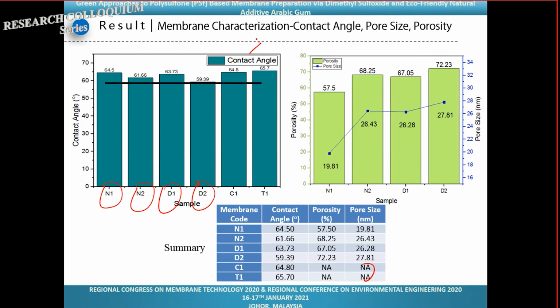So contact angle, what is contact angle? Contact angle is the measure of whether the membrane likes water or not. The lower the value, the better the hydrophilic. It becomes more hydrophilic for the membrane itself. So from the D, we can only compare N1 to D1, N2 to D2. So let's look at N1 and D1. For D1, you will have a slightly lower value as compared to the N1 value. Hence, D1 does show a comparable result.